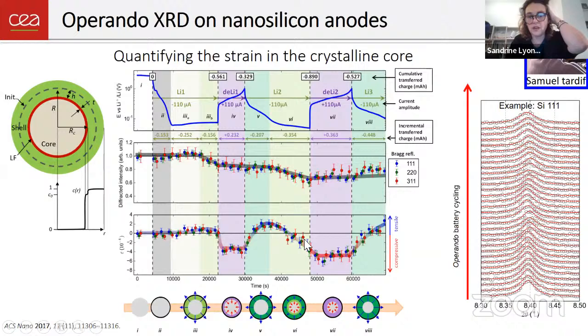That's the level of strain that you have in the materials that we could measure operando during the cycling. And that's a very important result because it's telling you when you are under tensile or compressive stress in the material, which is an important parameter because it will impact the performance of the material. So this is one first study, and a second one I wanted to show you is a different material, which